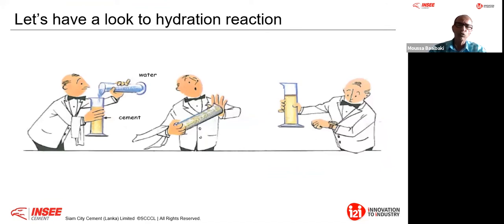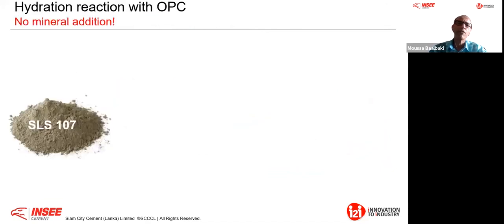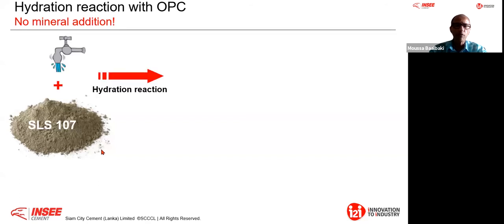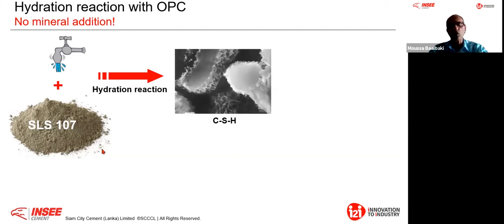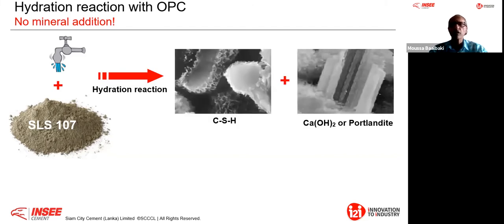Now, let's have a look at the hydration reaction. If I take, for example, the SLS 107, as I said, it has one constituent, clinker. You have minor additions below 5%. Of course, all cement you regulate with gypsum. Therefore, mainly it is clinker that will react here. If you add water to the clinker, you have a hydration reaction. You form two main products. The first one is calcium silicate hydrate, and the second one is portlandite, or calcium hydroxide. That is the same. Let's call it portlandite.